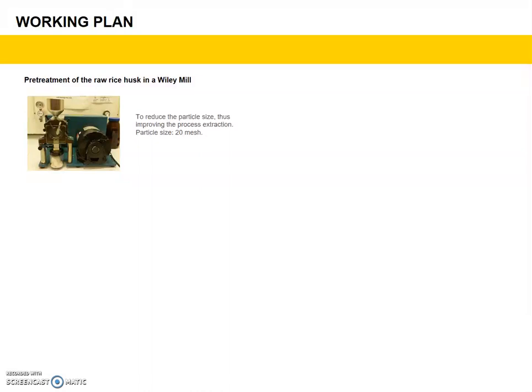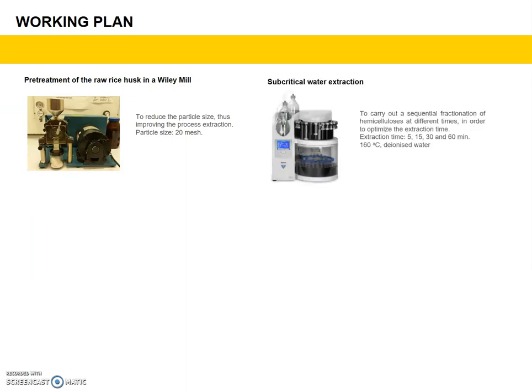This was the working plan carried out during the short-term scientific mission. First, the rice husk was milled using a Wiley mill to reduce the particle size to 20 mesh, thus improving the extraction process. Then, the extraction with subcritical water at 160 degrees was carried out at different times in order to optimize the extraction time. The resulting residue was used to continue with the bleaching and acid hydrolysis, whereas the extracts were freeze-dried for subsequent characterization.